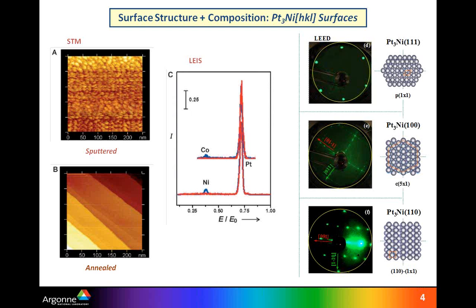As I like to repeat once more, catalysis is something which is happening at surfaces. In this particular case, we were focusing on platinum-3 nickel. On the right-hand side, you can see the LEED patterns of platinum-3 nickel single crystal surfaces. Each one has a unique arrangement of surface atoms. It's not only the arrangement that is unique; using low energy ion scattering, we were also able to see what is on the surface. As the results in the middle show, once the surface is annealed, due to segregation the surface is almost pure platinum, and there is very small contribution actually of nickel and cobalt.